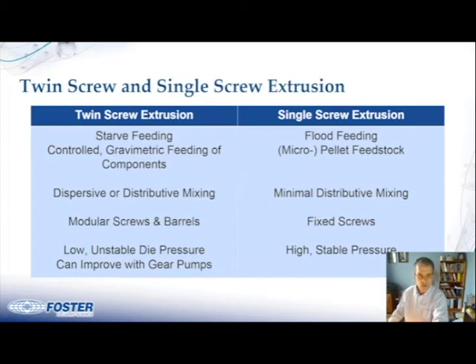And in twin screw extrusion, it has a very low, unstable die pressure. And with single screw extrusion, it has a very high, stable pressure. So the bottom line is twin screws are excellent mixers, but real low pressure, so they're not good pumps. And single screws are not great mixers, but they are excellent pumps. So you can see why both are used to create an implant. You can produce an implant directly off of a twin screw, and that's done by applying a gear pump, and I'll show how that's applied a little bit later on in the presentation.